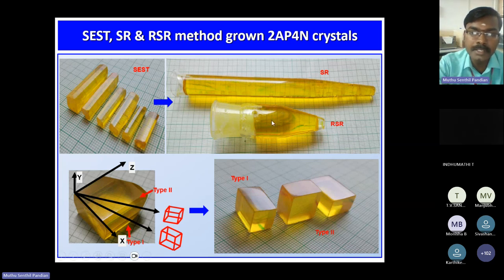And if you compare the physical properties and crystalline perfection of the conventional, SR and RSR method grown crystals, because of the less impurity segregation in the RSR method, the physical properties like optical transmittance, mechanical stability, laser damage threshold, and dielectric permittivity of the RSR method grown crystal are very high, superior compared to the SR and the conventional method grown crystal.